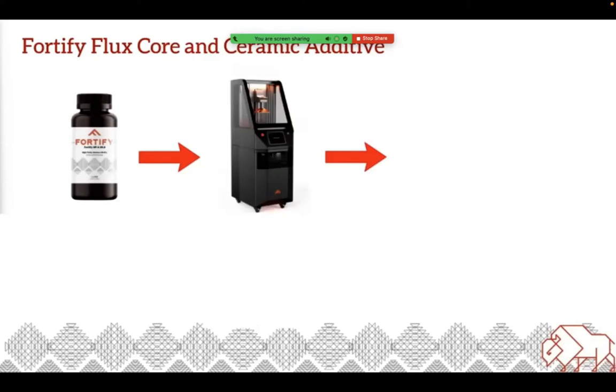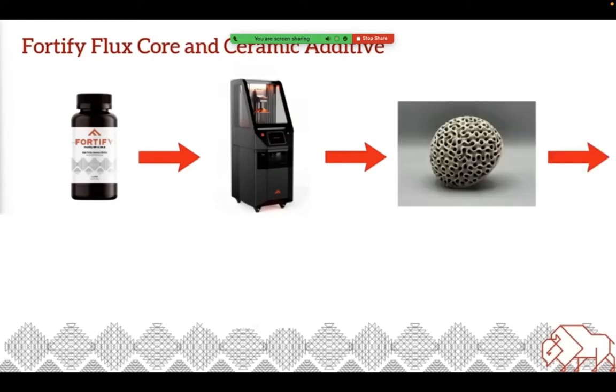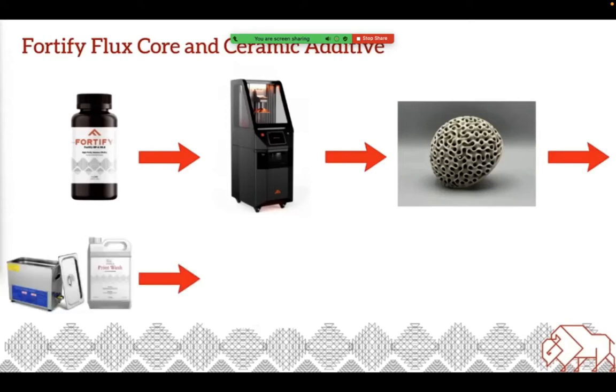We then pour in a UV resin that has been manufactured by Tethon here in Omaha. In this state, the material is a ceramic composite made up of ceramic particles and photopolymer resin. We then begin printing the file on the Flux. After printing the object via DLP layers, we then clean the part in a solvent wash or IPA to remove any excess resin. Unlike most UV resins, we do not post-cure the parts.